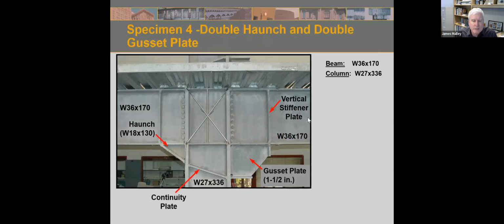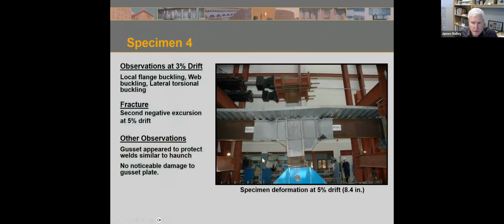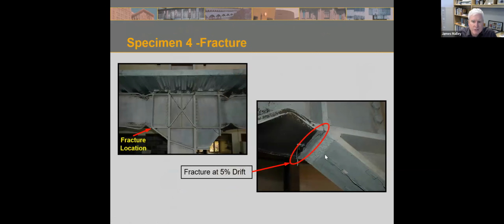So the fourth specimen is the double haunch with the gusset plate for the damper. And that's what that looked like at the end of the plate. That had thinner flanges, so we saw more buckling, but again, got out to 5% drift. And this is what a test looks like at 5% drift, so it's pretty dramatic. And you can see there, when the compression flange doesn't fully straighten out, it's because it sort of tips a little bit as well, and got good performance there. So it's very similar to test 2 as to when we got the fracture in the welds.